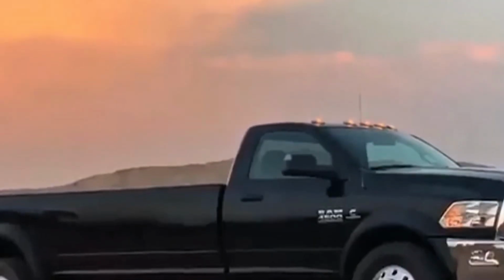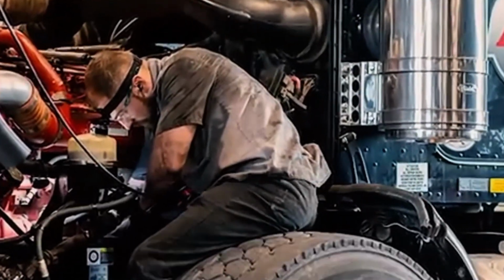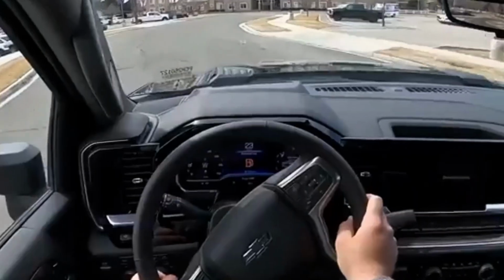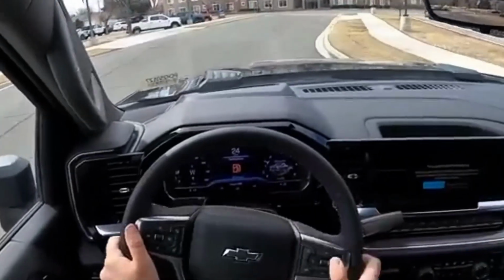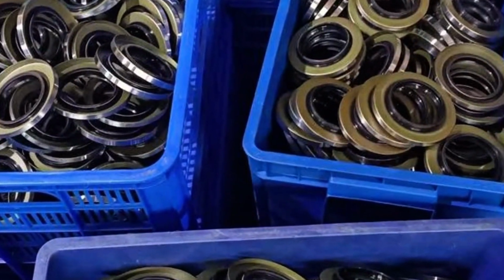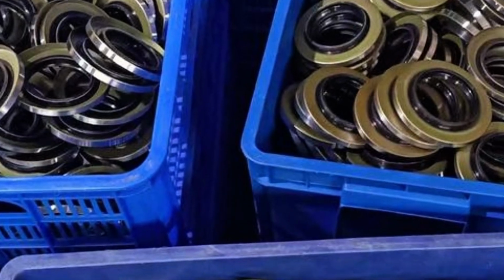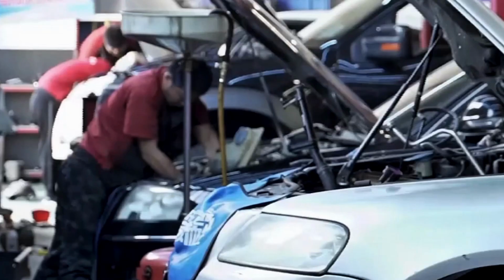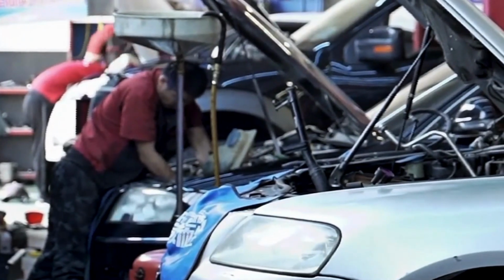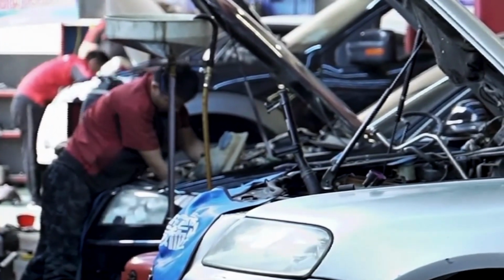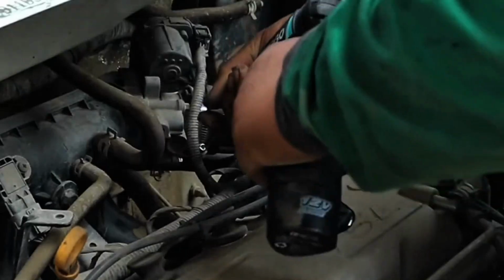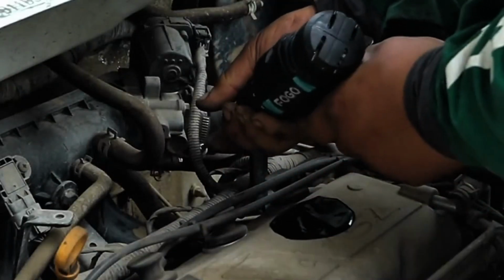Real-world results mirror this rule. One viewer with a light rear main seep saw a gradual reduction after several heat cycles and normal driving. Another with a split cam seal saw no change at all. That's not luck. That's the material state dictating the outcome. If your UV check shows a seep at an intact rubber seal, you've got a legitimate candidate. If you find structural damage or pressure issues, save your money.